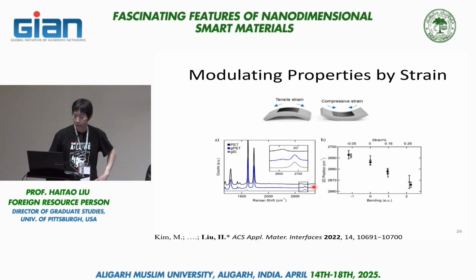what we are focusing on is the 2D peak. As I mentioned yesterday, the 2D peak is sensitive to a lot of environmental factors, and strain being one of them. If you apply strain depending on the direction, you can systematically shift this peak in both directions. A compressive strain would shift in one direction and the tensile strain in a different direction. And people have produced calibration curves. So based on this shift of the Raman peak, we can figure out, percentage-wise, how much strain we are imparting onto the graphene thin film.